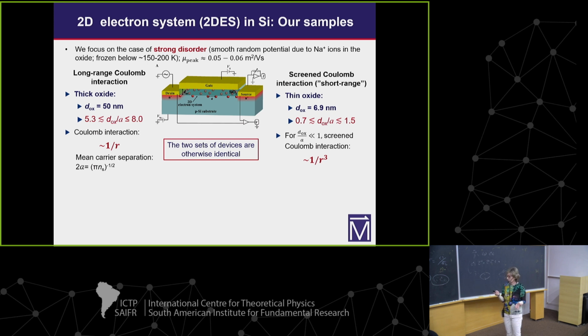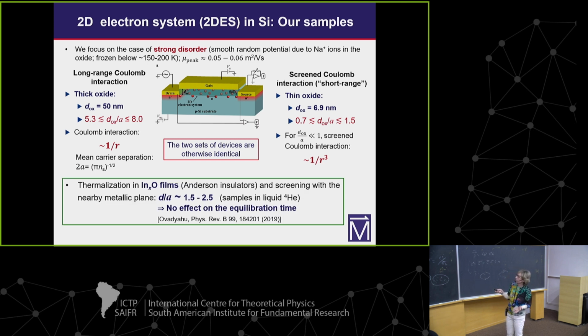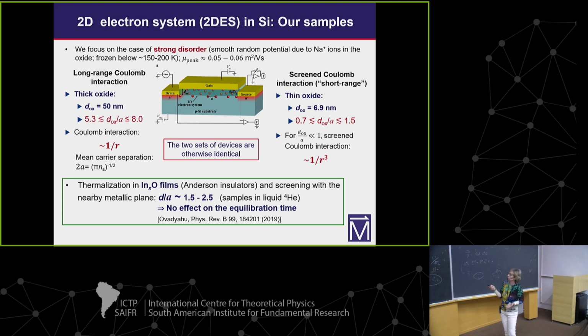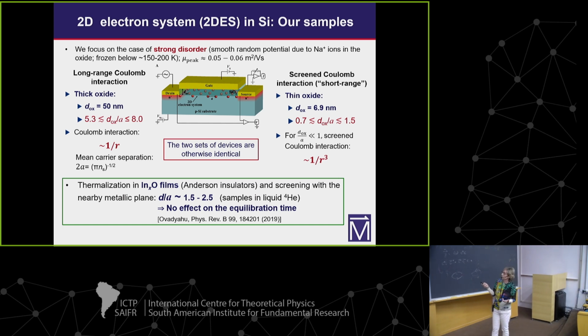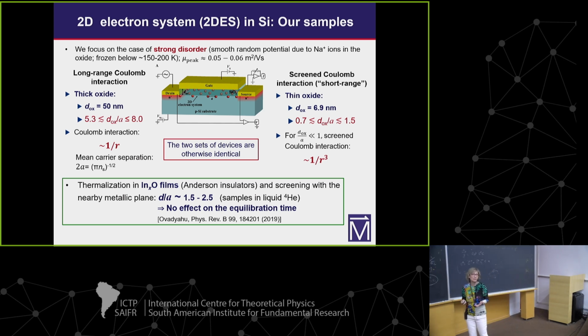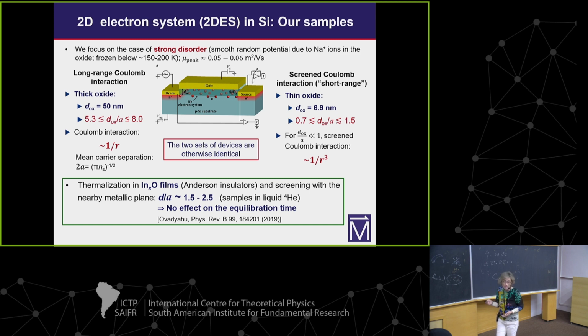And in the context of thermalization, there was a study of indium oxide films, which are Anderson insulators. They used this gate to try to screen the Coulomb interaction, but there was no effect on the equilibration time. I don't know why, but I noticed that in their case, the screening was not as good as in our case. Also, they had samples immersed in liquid helium, so they were strongly coupled to a thermal bath, in contrast to our case.